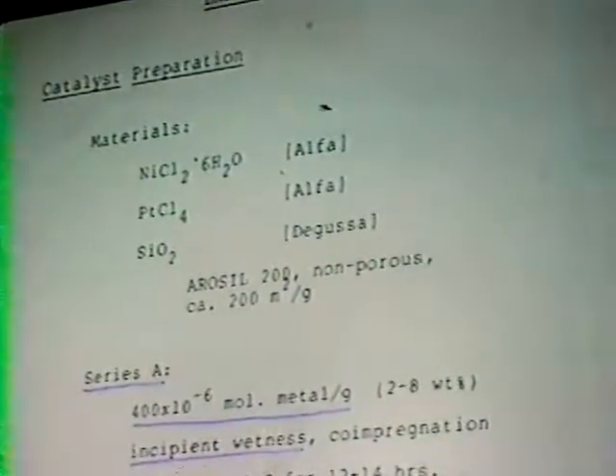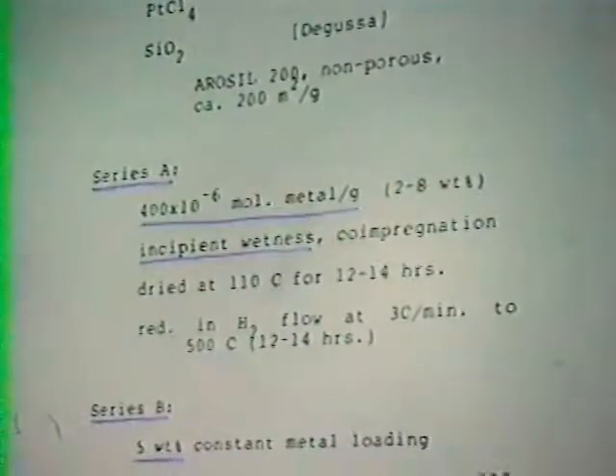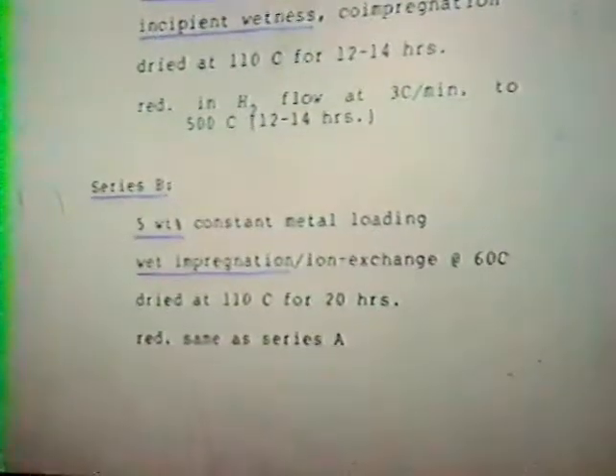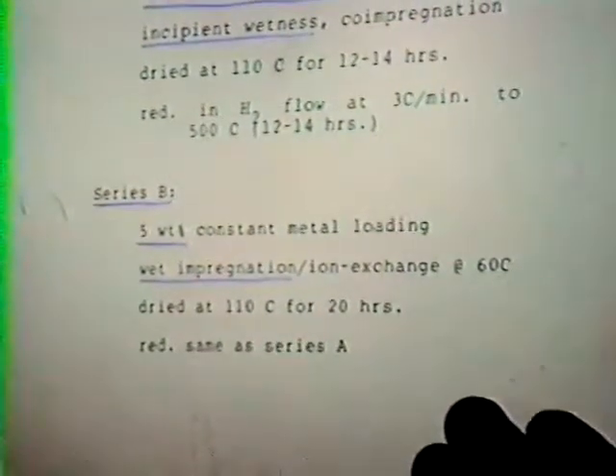And Series B, which was a constant weight loading of 5 weight percent, which was an earlier study, which was wet impregnated, but with that type of preparation there could have been some ion exchange going on simultaneously. We used a wide variety of techniques, including TPR of the catalyst precursor, TPR of the oxidized reduced catalyst, as well as chemisorption, XRD, etc., and also some reaction studies. I'll briefly mention some of the CO hydrogenation results here.